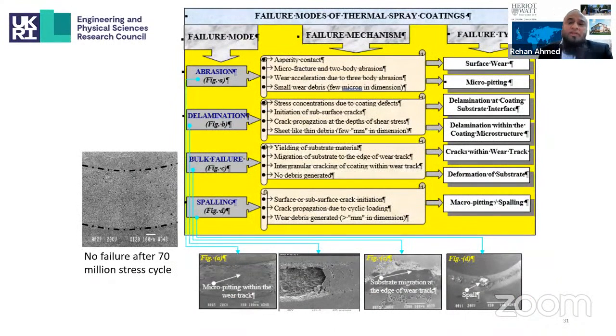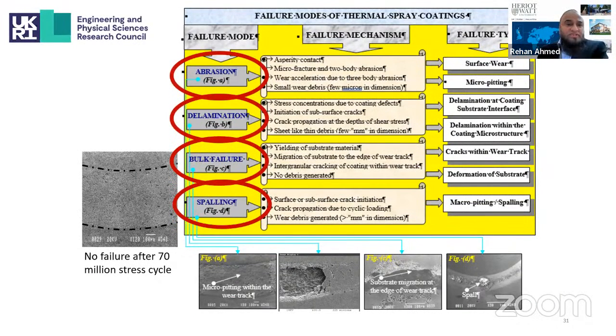So the failure in rolling contacts can be classified, apart from delamination, into 3 other categories, such as abrasion, bulk failure, and spalling, as shown in this slide. And the SEM observations here indicate the morphology of these failures. And if we fully understand these failure modes, it is possible to design coatings to stand 70 million stress cycles without failure, which is generally the industry's standard for bearings. And I will look at that in the next slide.